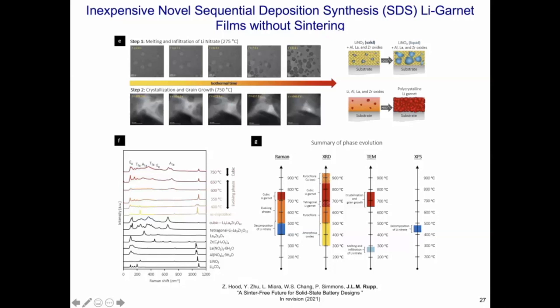So it's an amorphous film of the other metal cations that form. And in it, you have actually already the lithium salt that is trackable by the signal. So it's a composite that you first form. Then you do an annealing. We actually start at some point, when we go higher in temperature, to melt and decompose. So you can see here a melting, in transmission electron microscopy, of the lithium salt in the preformed film.